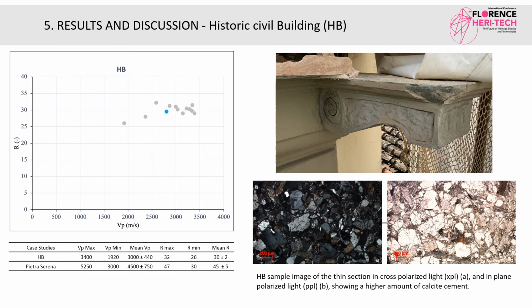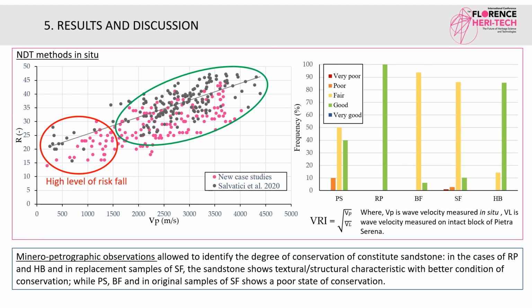The Vp and R values recorded of historic civil building corbels indicate stone with good mechanical properties. From mineropetrographic observation, the stone presents similar characteristics of the RP sample, a higher amount of calcite and a lower porosity, which makes the rock compact. The distribution reported in Salvatici et al. is implemented with the new case studies.